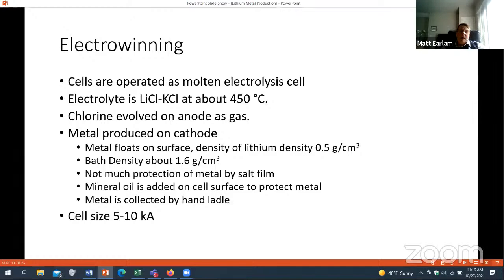So in this process, lithium metal is very, very light. It's less dense than water, which is kind of interesting. It's about 0.5 gram per cubic centimeter. The bath density is about 1.6. So because it's so different in density, there's not a lot of protection of the salt film on top of the metal if it's floating on top of the bath. And so the way that this is modified is that they add a mineral oil to the surface, and that floats on the electrolyte and protects the metal a little bit so that it doesn't oxidize so rapidly. The metal is collected by hand ladling, and this whole process takes place in a dry room.